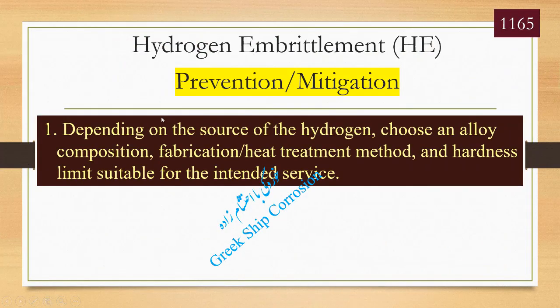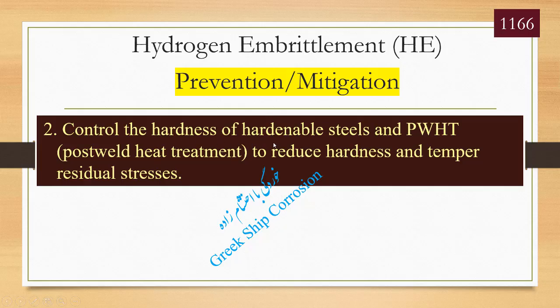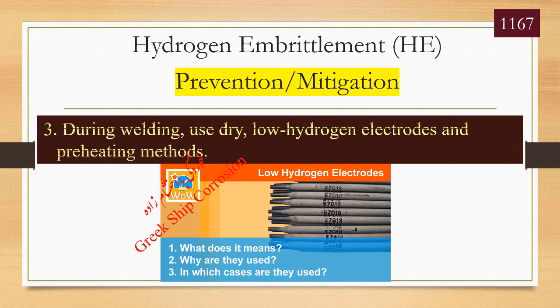Prevention and mitigation. 1. Depending on the source of the hydrogen, choose an alloy composition, fabrication, and heat treatment method and hardness limit suitable for the intended service. 2. Control the hardness of hardenable steels and use post-weld heat treatment to reduce hardness and temper residual stresses.